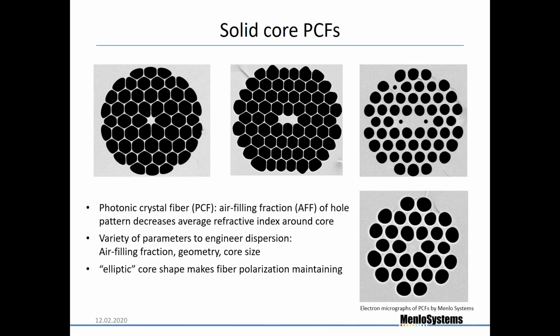It will make it birefringent, so the two polarizations will see different refractive index, and therefore, when you bend the fiber, when you curl it up, you induce stress birefringence, but this induced birefringence will always be weaker than the intrinsic birefringence that comes from the geometry of the core, and so you're unable to alter the polarization state, and the polarization will be preserved under any circumstances. And the main application for these fibers is supercontinuum generation.